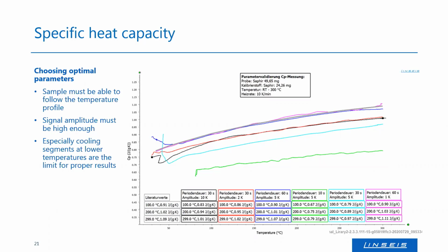And the result, the gray line, by the way, is the literature. And with the purple and the blue, we hit the literature values pretty well. But the faster we go, the lower our omega is, so the period, the worse the result will be. So there are some optimum settings here. Mostly I use a 60 seconds period and an amplitude of roughly 1 Kelvin, sometimes 0.5, sometimes 2 Kelvin or something like this. But this will lead to the best results for this heating rate and this sample.